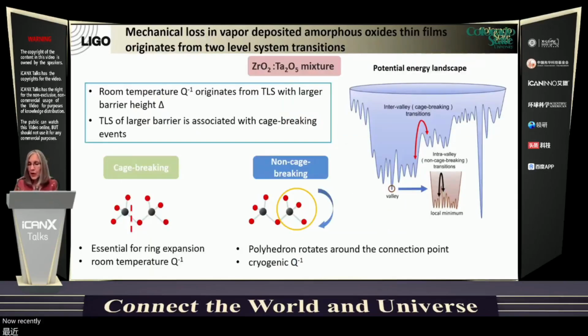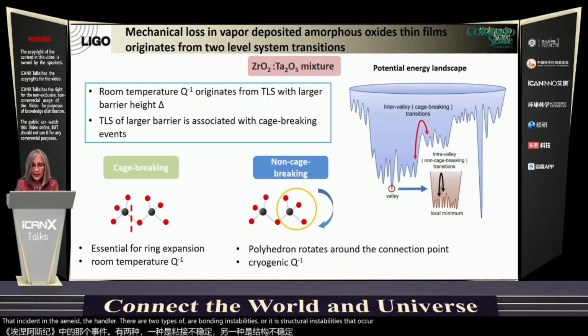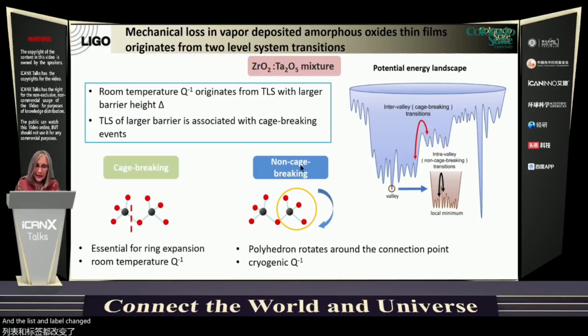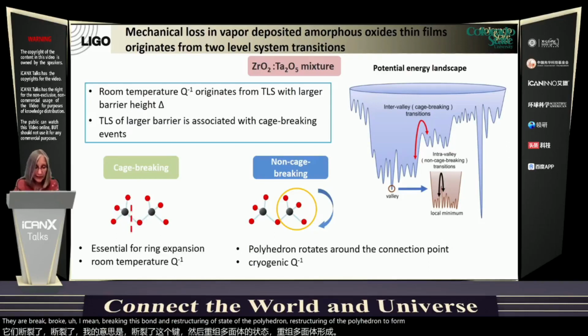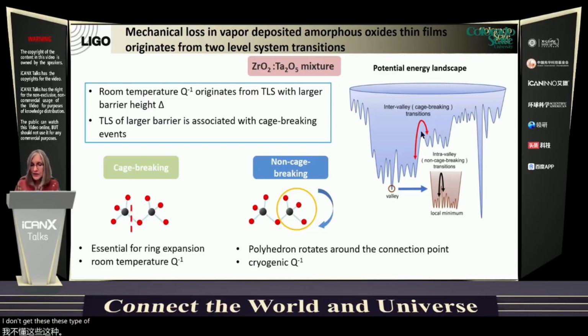Now, recently, our colleagues at the University of Florida have shown with model simulations that in zirconia tantala, there are two types of bonding instabilities or structural instabilities that occur at the medium range. Those are labeled cage breaking and non-cage breaking transitions. Cage breaking transitions involve, for example, breaking this bond and restructuring of the polyhedra to form larger rings. These types of transitions in the potential energy landscape correspond to transitions that have large barrier heights.